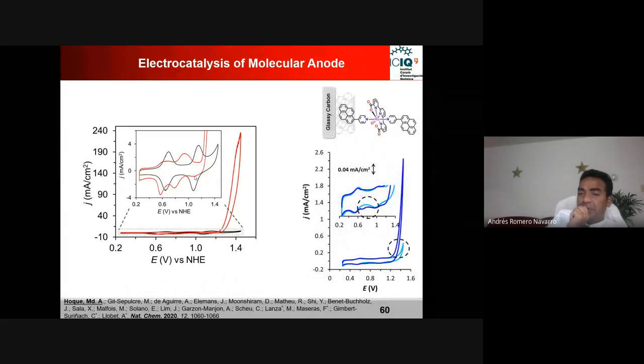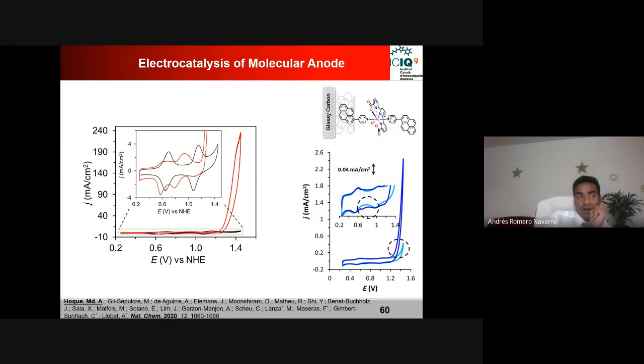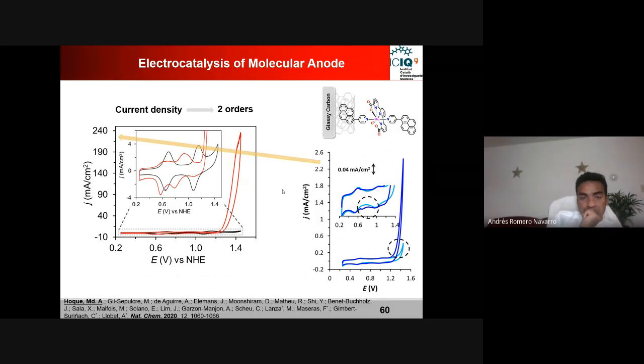And then, if we compare our system, we have this mononuclear compound that we prepared for making this molecular anode through this pi-pi interaction. And now, if we compare the values under identical conditions, we have seen the current density improve by almost 2 orders of magnitude. So that is also another breakthrough in our molecular water oxidation field.